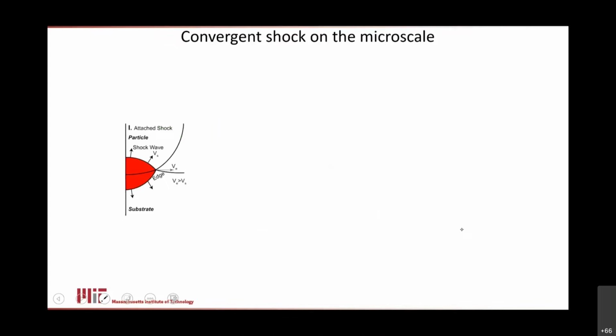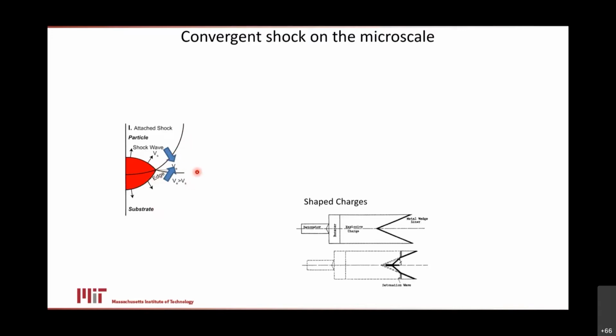So the reason we think this is because our geometry is what you might call a convergent geometry, and it's a shock problem. So we have here a particle which is shooting down and impacting a substrate. And in this geometry, we're producing shock waves at the contact, and those shock waves are interacting with the particle and the substrate sort of clamping shut, right? So there's a V-shaped geometry here as these two surfaces clamp shut together. And that geometry is sort of a familiar one in the shock world. If you think of a shaped charge and a shaped charge liner, of course, this is a convergent shock, and it's well understood that the collapse of this V shape leads to a hydrodynamic condition that shoots a jet out the center.